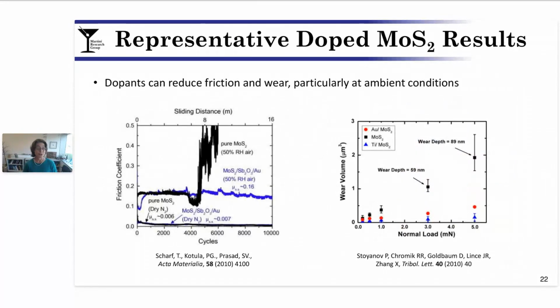Shown here are a few more representative results, in this case for doped MoS2. On the left, I'll draw your attention to the top black and blue lines. The black line represents pure MoS2, and the blue line represents antimony oxide gold doped MoS2. And right away, you can see that the blue line runs much, much longer than the black one, indicating longer wear life. On the right plot, we're looking at wear volume as a function of load. The black data is the pure MoS2, and the blue and red are the gold or titanium doped MoS2, and we can see lower wear with the introduction of the dopants.